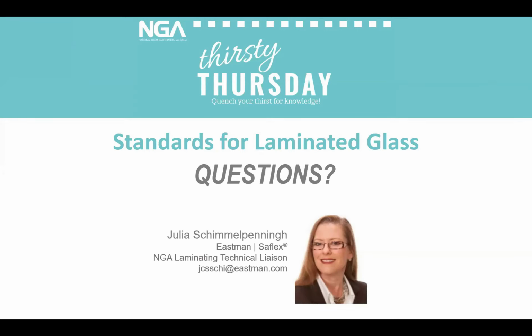And that is why the Pummel test requires that you rate both sides and to make sure of what you're getting. You can also have things like coatings and inks and things like that that can cause an interference or have an altering effect on the adhesion of the interlayer to that glass surface. And you want to know those, and you can very easily see those in the Pummel test. If you have certain designs or things like that, they do come out. You can actually see them.